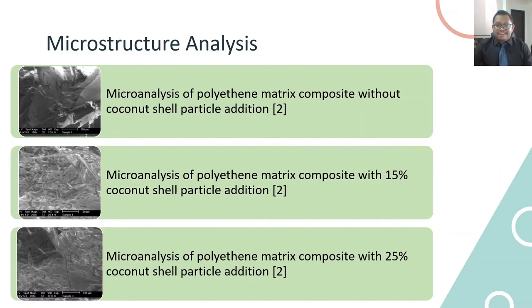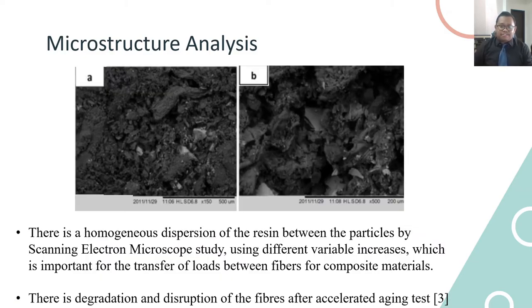This explains the reduction of strength within the composite matrix structure with an increase in the content of the coconut shell particle. The increase in hardness is due to an increase in the percentage of particles of coconut shell within the composite matrix. The next figure shows the result of SEM by Fiorelli. There is a homogeneous dispersion of the resin between the particles by scanning electron microscope study using different variable increase, which is important for the transfer of loads between fibers for composite materials. There is degradation and disruption of the fibers after the accelerated ageing test, as shown in the figure.